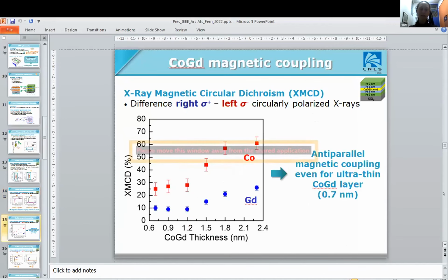We did this for the whole thickness range, between 0.7 nanometer and 2.3 nanometer. And you can see that the percentage of XMCD increases with increasing thickness. This is only because with increasing thickness you have more magnetic material, and so the percentage of XMCD increases. But for the whole range of thickness, we always have an anti-parallel magnetic coupling between the two lattices. So even at 7 angstrom, we have two sublattices that are coupled.